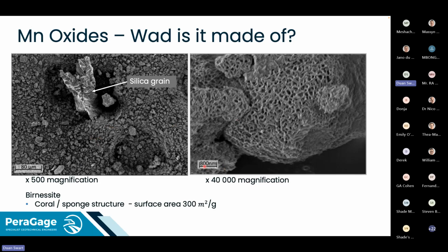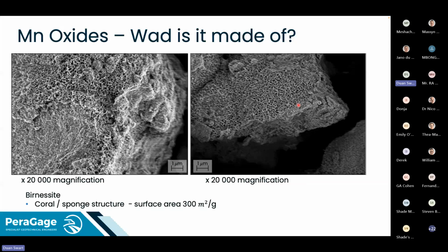If you zoom in on one of those, this is birnessite. It typically has a coral to sponge type structure, and its surface area is very, very high. It's 300 meters squared per gram. Your smectites are sitting at 600, so you're very close to that. There's not many minerals that have such a high surface area, and because it has such a high surface area, it can take up a lot of water. You can see that it looks like a sponge or coral, and that can suck up water quite a lot. This is just more photos of the birnessite.